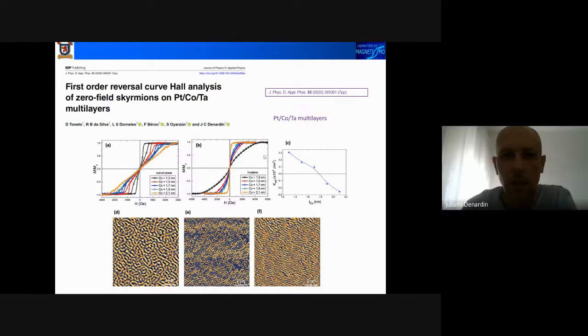So the films with different thickness change the anisotropy from out of plane for 3 samples to in plane for the last 2 samples. And the intermediate sample, with cobalt 1.7 nanometers, is the sample that has intermediate anisotropy. It has the smallest anisotropy, the sample that is in the transition between in plane and out of plane. This is still out of plane, but is almost an in-plane sample.